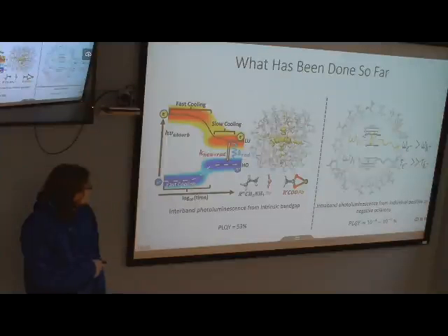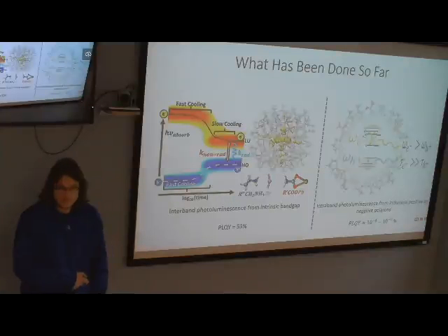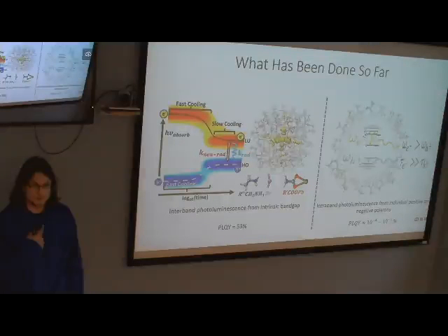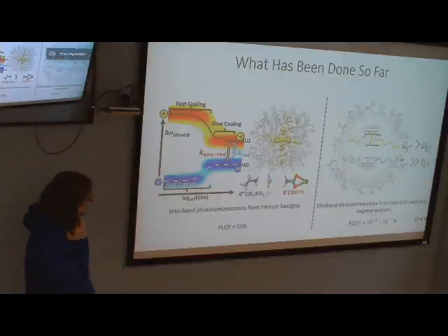We calculated that for a negative polaron and a positive polaron separately, and we got fairly small yields computationally, and this is something that, from what I've seen, hasn't been looked at experimentally yet. People who have looked for photoluminescence signatures of polarons have seen absorption characteristics. So that was the motivation for looking at photoluminescence, because they are optically active in some sense. And on your left is visible and right is infrared.